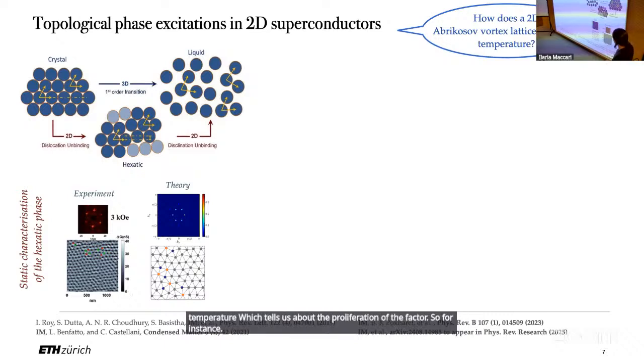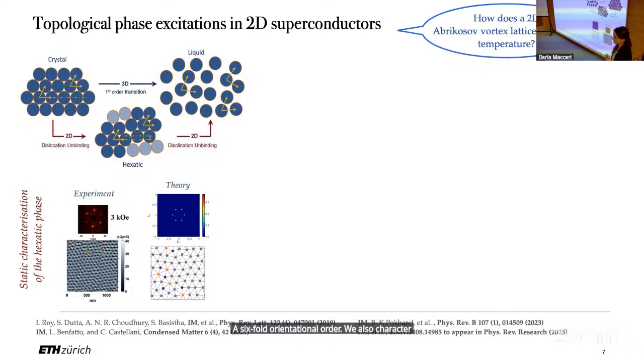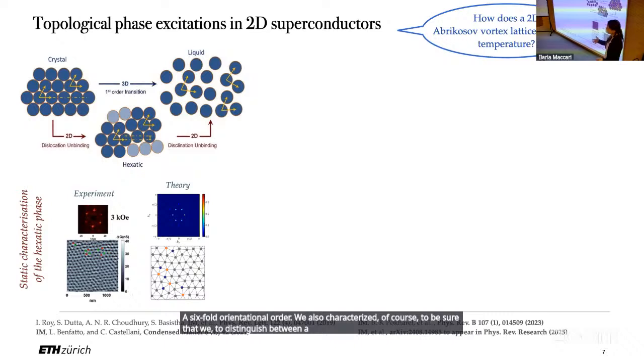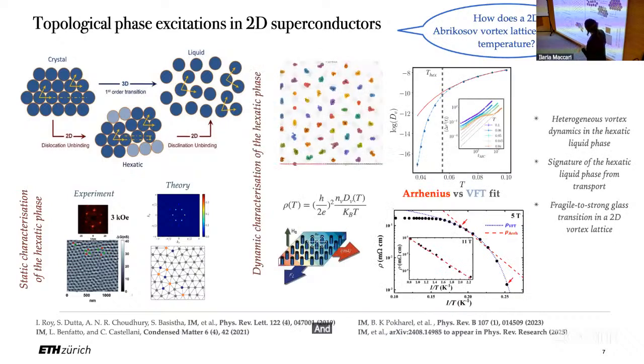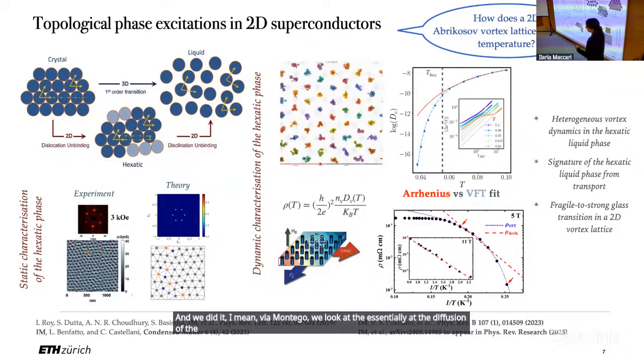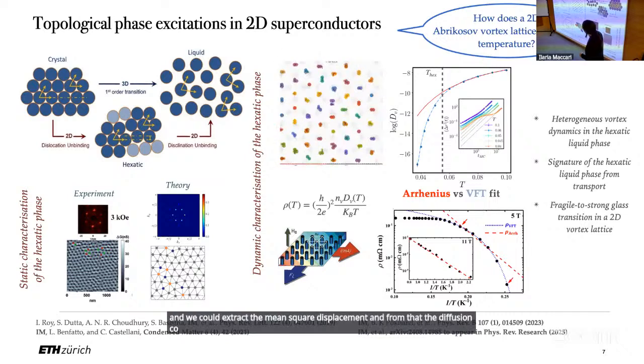So for instance, this is an example of measurement and Monte Carlo simulations in this intermediate state where you see the presence of these dislocations, this kind of defect, but still you can see from the structure factor that you have these 6 spots indicating that there is a 6-fold orientational order. We also characterized, of course, to distinguish between a liquid phase and a solid state, we need to probe the dynamics to see how the system responds to some external forces. And we did it via Monte Carlo. We look at essentially the diffusion of the vortices via thermal energy. We track each vortex in time individually, and we could extract the mean square displacement, and from that, the diffusion coefficient as a function of the temperature.